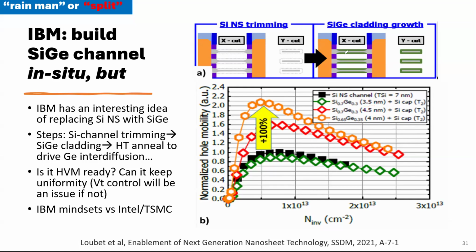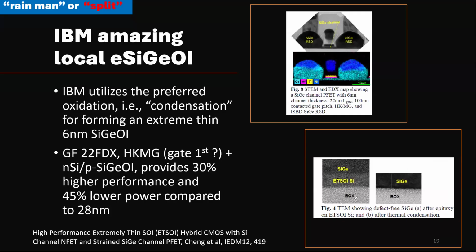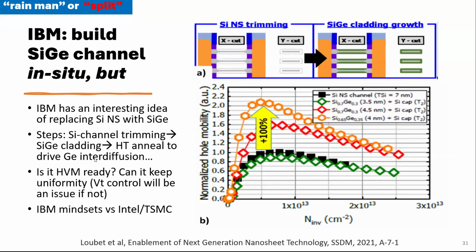And then you put cladding there, and then you heat it up and do the condensation, as if you are trying to do this. For the ETSOI, you put SiGe here, and you condense it. So I want to do the same thing for nanosheet. Can I do that? A similar idea, like condensation, to force germanium to diffuse in. Not by condensation, just pure annealing, right? There's no oxidation here, just pure annealing. Can you do that? Yes, you can try that.